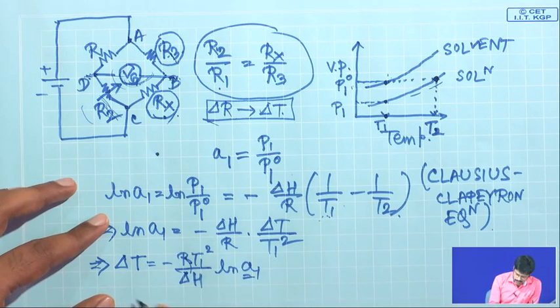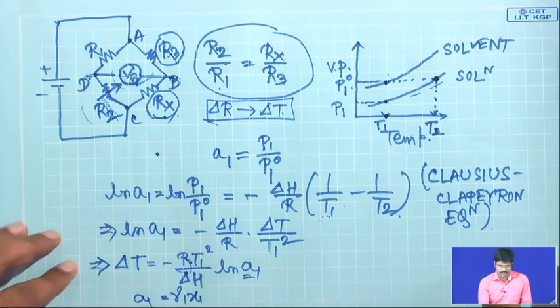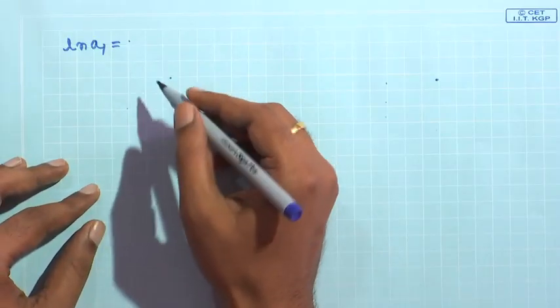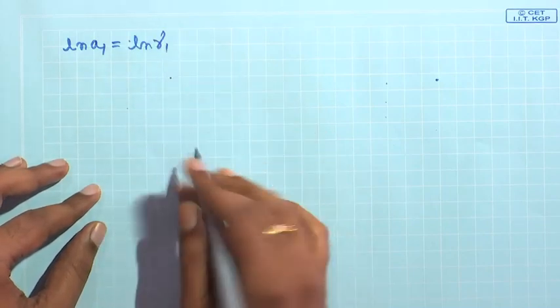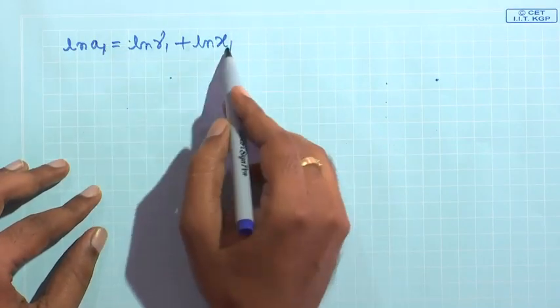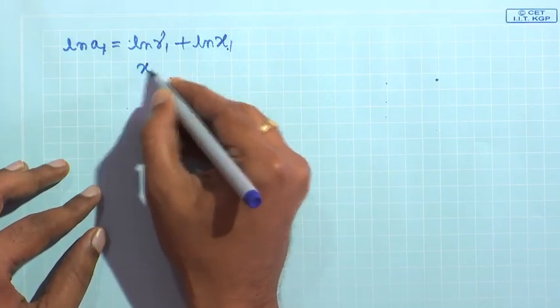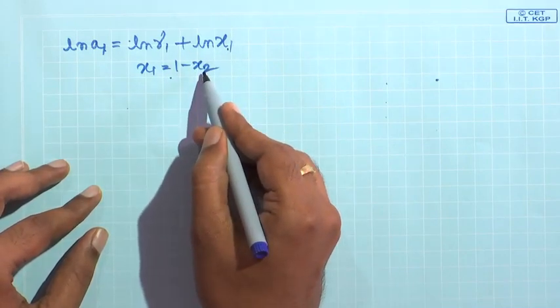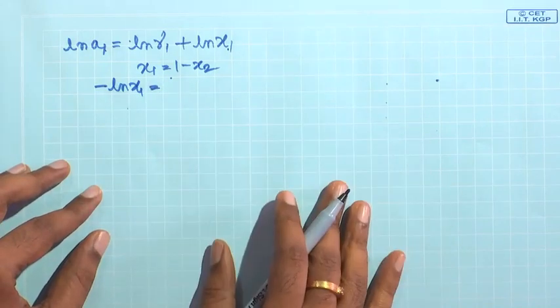A1 = gamma_1 × x1, where gamma_1 is the activity coefficient and x1 is the mole fraction. So ln(A1) = ln(gamma_1) + ln(x1). Now x1 = 1 - x2, and x2 is very small since it is a very dilute solution. It can be shown that -ln(1 - x2) can be written as a power series: x2 + (1/2)x2² + (1/3)x2³ + ..., and for very small x2 we keep only the first two terms. This mathematical treatment is to simplify and correlate delta_T with delta_R and molecular weight.